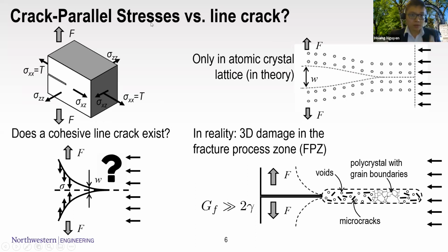So why crack parallel stress? We see why crack parallel stresses matter. Now we see how. Imagine a thought experiment where you have a block and we have a crack, and the block is subjected to several crack parallel stresses, sigma ZZ, sigma XX, and sigma XZ. In the cohesive crack model or LEFM based model, you have only the line crack, and any existence of the parallel stress will not cause any change in the stress field.